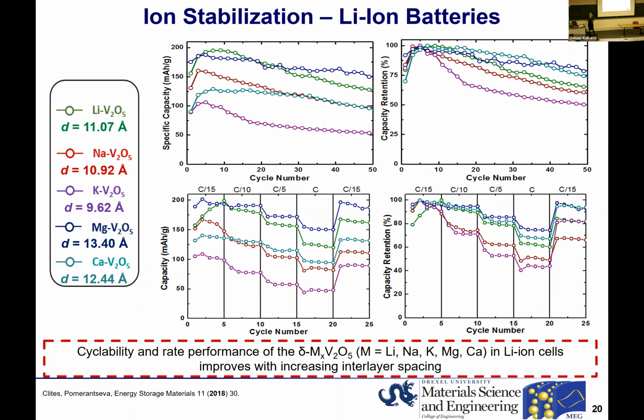And we already had 5 materials that we synthesized, so naturally we just cycled all of them in lithium-ion batteries. And in this case, the lithium pre-intercalated phase is more of a reference, but remember, we observe improved diffusion in this case when the chemically pre-intercalated ions and the electrochemically cycled ions are the same.